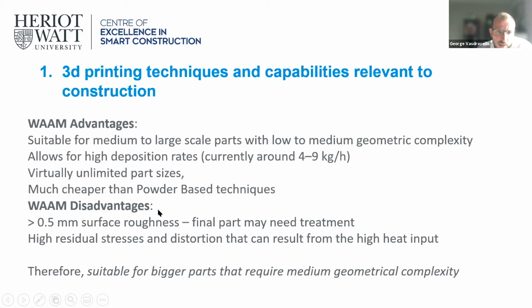The disadvantages are, first, the surface of the final product is quite rough. The roughness is more than 0.5 millimeter, even 1, 2, or 3 millimeters rough. So the final part may need further processing to make it smooth. And I would say the most important disadvantage is that due to the heat input of the technique used, we have high residual stresses and distortion in the final part. And therefore, all this should be, of course, taken into account in the design. Therefore, this technique is suitable for bigger parts that require medium geometrical complexity.